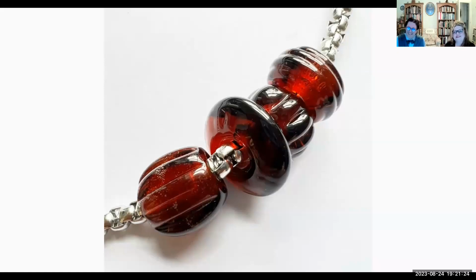Wow. The one in the end is done the super modern way with a thing called a bead roller, which is a graphite mold. So you get your glass onto your mandrel and then you use the marver to actually do some of your shaping. The disc bead is there really because you don't see a lot of those in the Viking beads, and that's because structurally it's a less sound shape. When you come up towards the edges, it's a bit more fragile. And I would guess that when I look at Viking beads, all of them are shapes that you could shape with gravity. So you get the mandrel, you get it hot, you keep turning, and gravity sorts out your shape for you. That one there, you could do it with gravity, but you'd be there for a really, really long time.